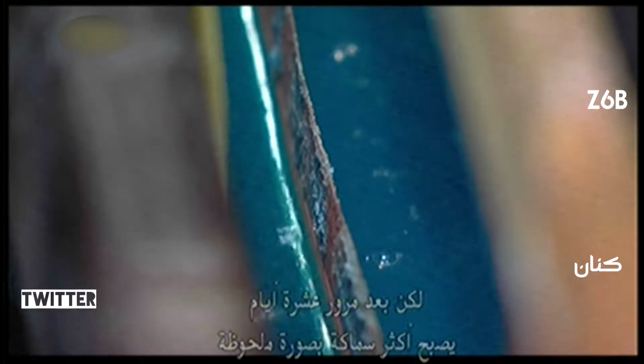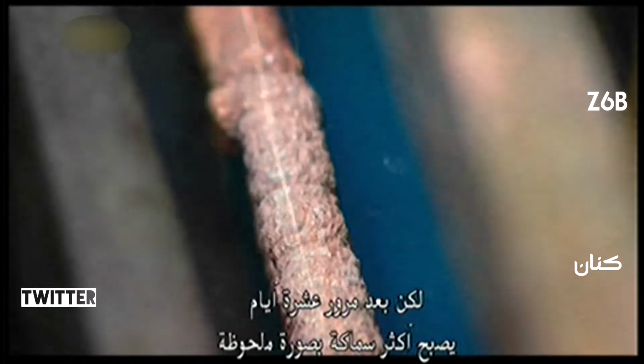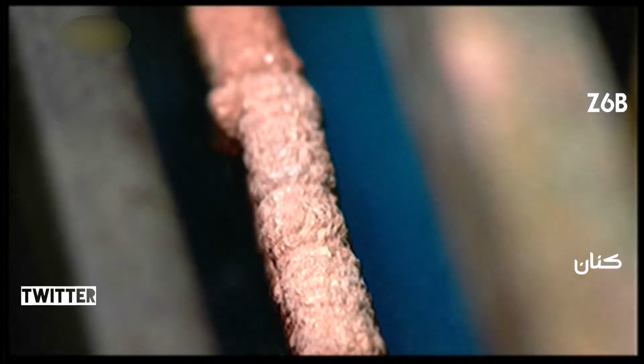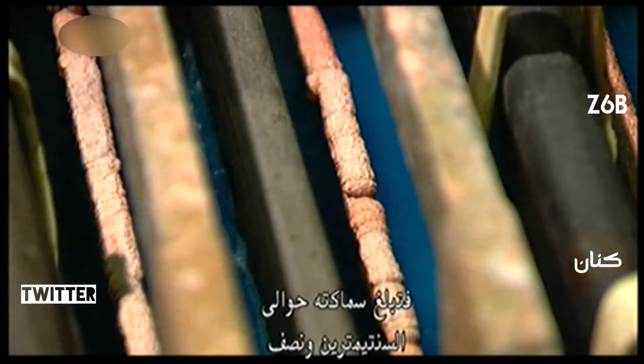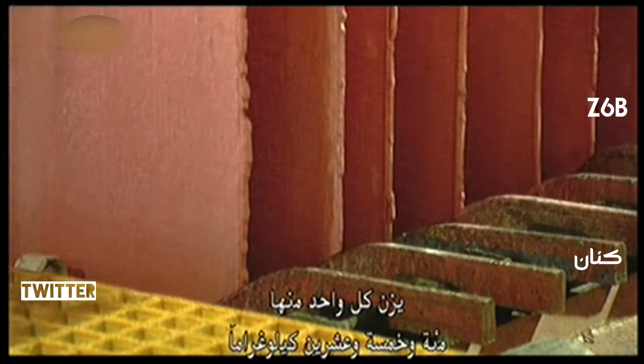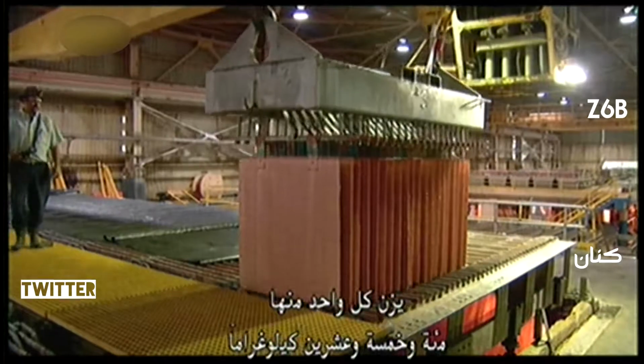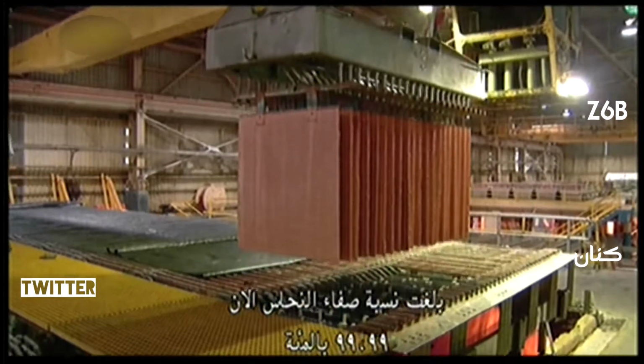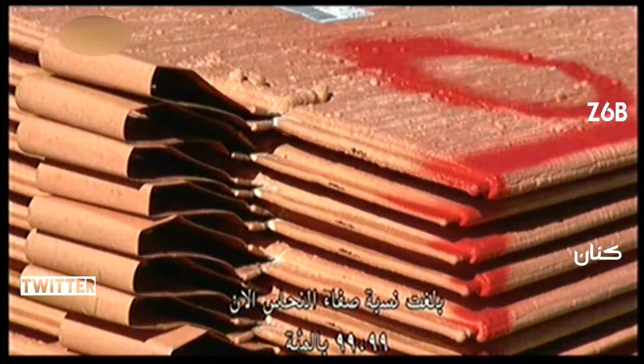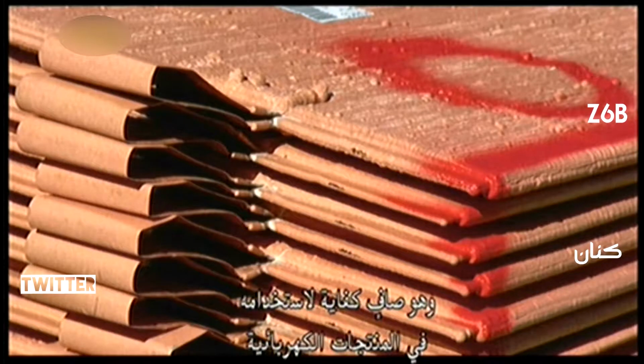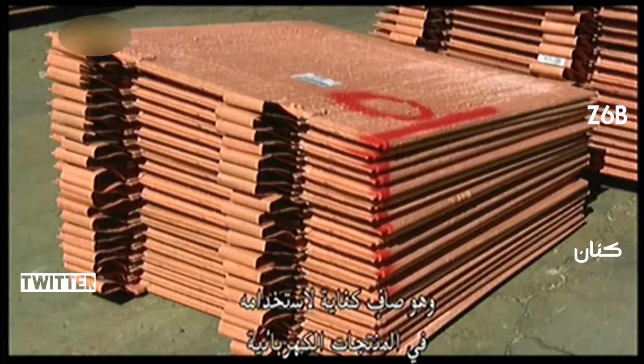Initially, the cathodes are wafer thin, but after 10 days, they've thickened substantially, becoming around 2.5 centimeters thick. Each one weighs around 125 kilograms. The purity of the copper is now 99.99%, pure enough to be used in electrical products.